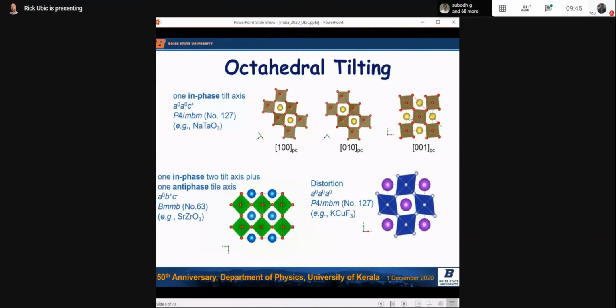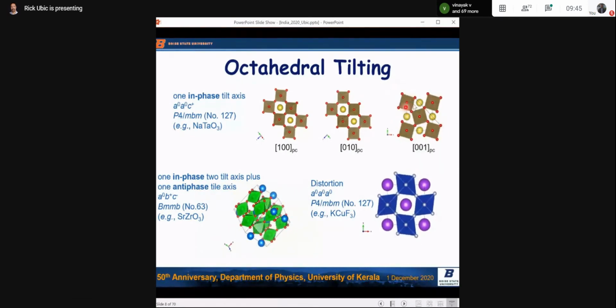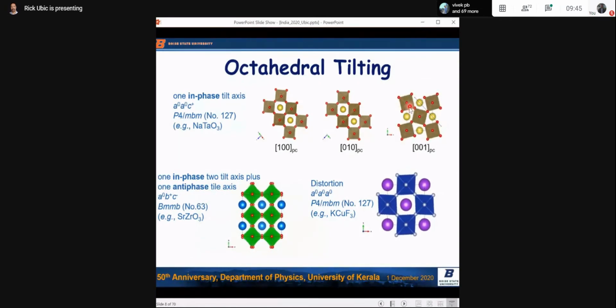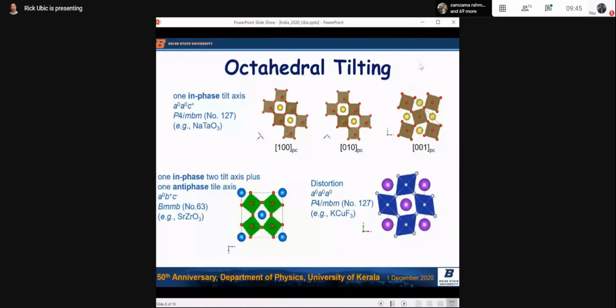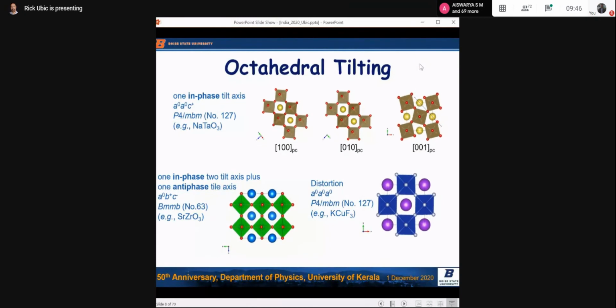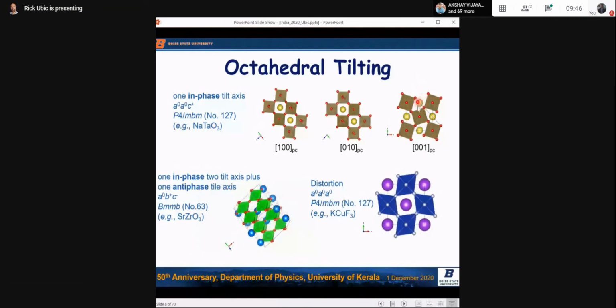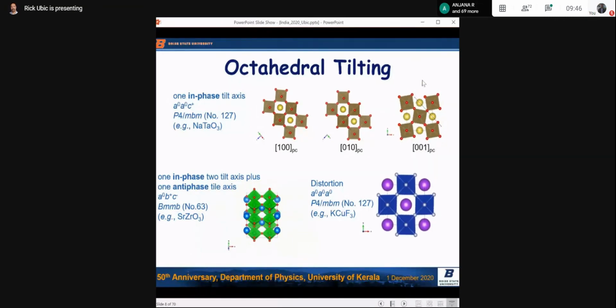The other thing to notice here, it's kind of more subtle: as these octahedra tilt, you see how they grow? They're small here, and then they grow, and they get smaller as you untilt. That's actually important because as the tolerance factor goes down, these tilts increase. The reason they increase is that when the tolerance factor goes down, it generally means the A site is getting small. If the A site gets too small, the space that it occupies is too big for it, so the octahedra tilt to take up some of the space. That's how the structure is linked, like that.